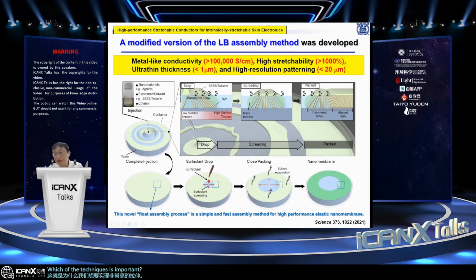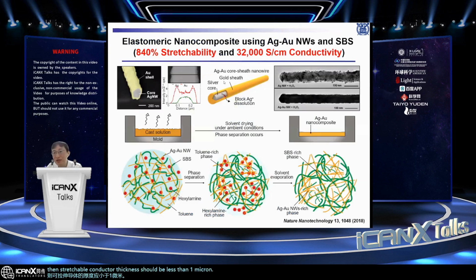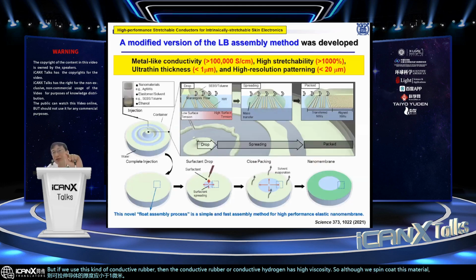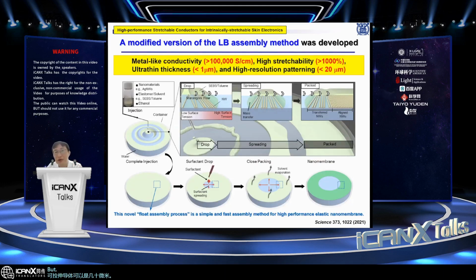Ultra-thin thickness is important. If you take a look at the cross-section of an electronic device, a semiconductor device, then the typical thickness of the interdielectric layer or metal interconnection is usually less than 1 micron. That means if we want to make a vertically integrated multifunctional skin electronic device, then the stretchable conductor thickness should be less than 1 micron. But if we use this kind of conductive rubber or conductive hydrogel, it has high viscosity. So although we spin coat this material, the thickness of the stretchable conductor can be tens of microns. But we want to achieve a micron thickness.